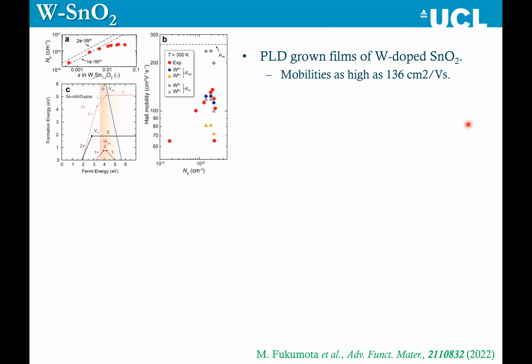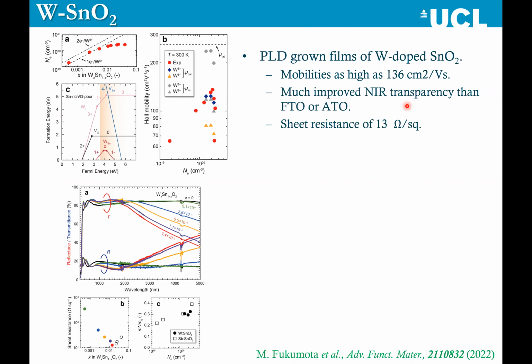But we weren't limited just to looking at tantalum. We also looked at tungsten as a dopant. And we did this in collaboration with a group in Japan. And what our calculations showed is that tungsten is a very low energy dopant. It injects electrons directly into the conduction band. It forms as tungsten 5+, not as tungsten 6+. And in fact, the samples showed mobilities as high as 136 centimeters squared per volt second, which would be a world record for doped tin dioxide.